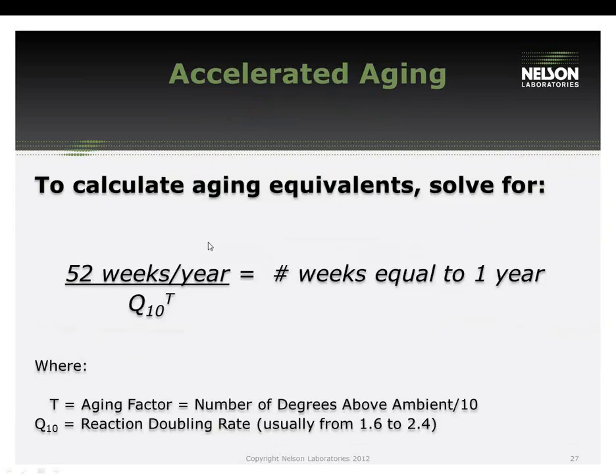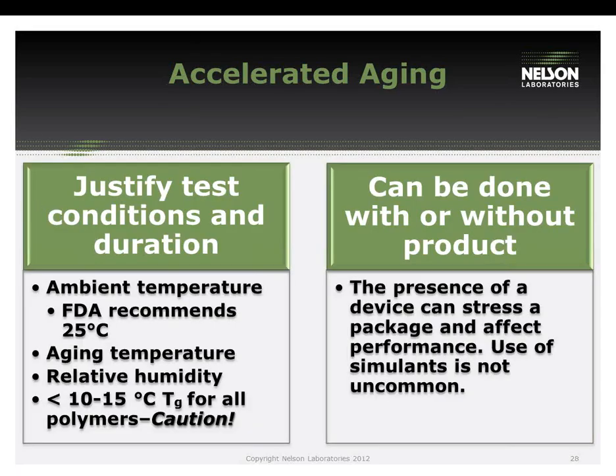This is the equation, and it calculates the aging factor, which is the temperature that you want to use above ambient. Normally tests are aged at 55 degrees. Additionally, we are using a Q10 reaction doubling rate, which is normally a value of 2. I've only seen one person change this value, and it was a packaging engineer that was very smart and knew all about the thermal glass transition points of the plastics involved in their product, and was able to calculate a value of 1.8 for his Q10 versus the conservative value of 2.